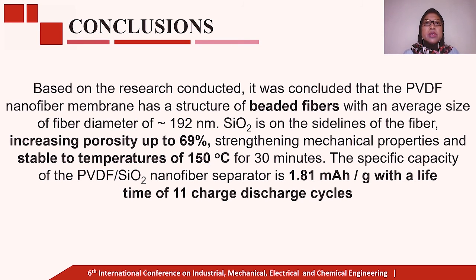Finally, conclusion. Based on the research conducted, it was concluded that the PVDF nanofiber membrane has a structure of beaded fiber with an average size of fiber diameter of around 192 nanometer, increasing porosity up to 69%, strengthening mechanical properties and stable temperature of 150 degrees C for 30 minutes. The PVDF SiO2 nanofiber separator specific capacity is 1.81 mAh per gram with a lifetime of 11 charge-discharge cycles.